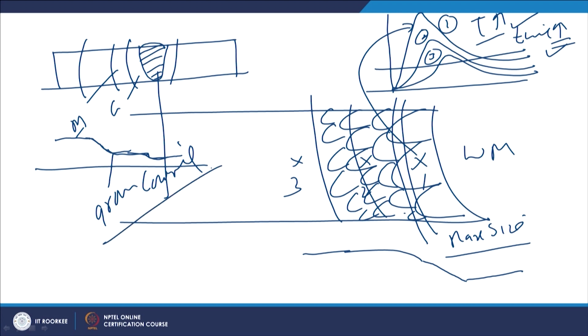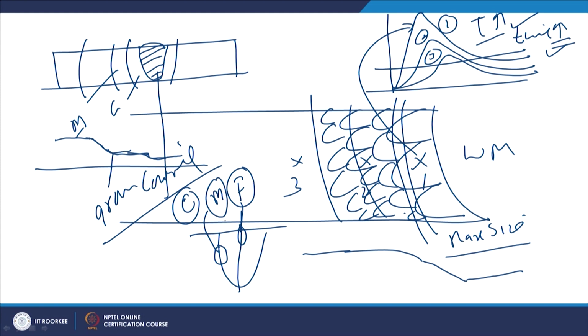Now, as far as the weld metal is concerned, in general the weld metal also shows a lot of variation in the grain size. The finest grains are observed at the center of the weld, and then maximum grain size is observed at the grain boundary. So, there will be coarse grain size at the grain boundary and the weld center will have the fine grain size, and medium grain sizes will be available in between. So, again there will be variation in the hardness in the weld metal itself like this. So, the maximum hardness at the center and then reducing hardness up to the fusion boundary, and this is also attributed to the changing grain sizes.